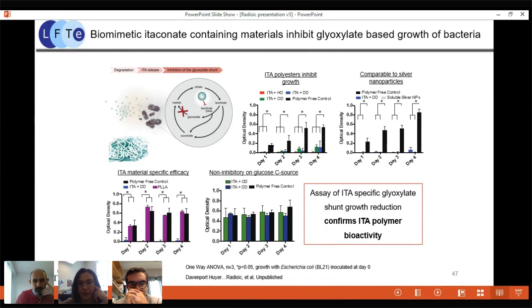So what Locke was able to capture here with these polymers as well, outside of the body in vitro settings, is that we can inhibit growth of E. coli on acetate, which really shows that we have mechanism-specific inhibition of growth. And this is done by itaconate and not by side effects of other polymers. And you can see that really if we compare under those conditions itaconate to silver, we can see very similar levels of inhibition. So that what the polymer is releasing is really a functional form of itaconate.